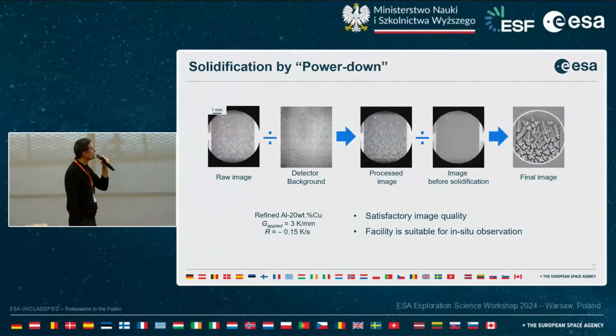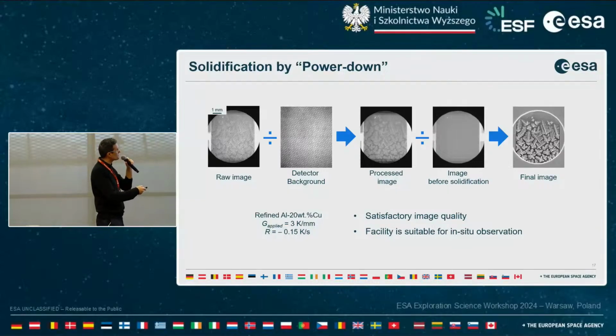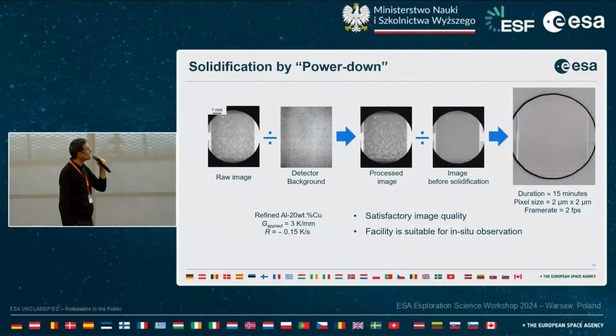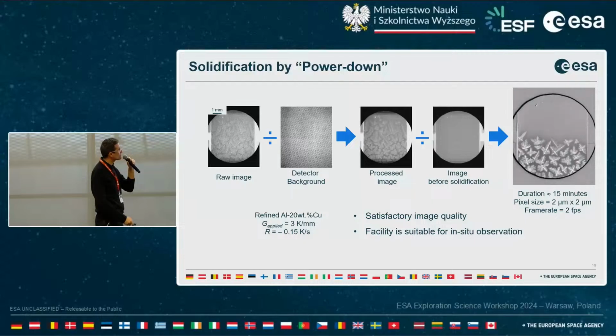These are typical images that were collected during the breadboard test. The raw images require some detector background correction and additional processing in order to obtain very nice pictures where we can clearly distinguish the dendrites and the surrounding liquid. In this new device, the image quality was very satisfactory, and the facility is clearly suitable to carry out in situ observation. You can see here an example of a movie that was obtained.